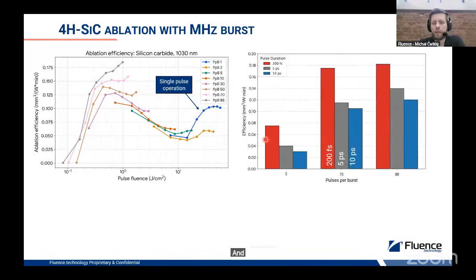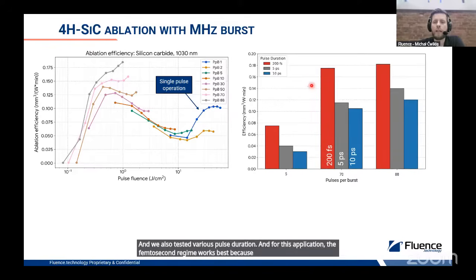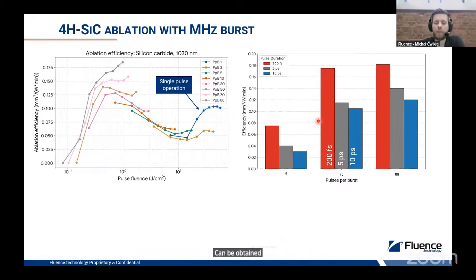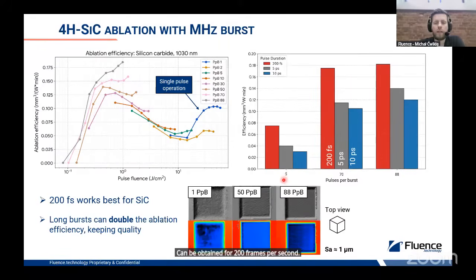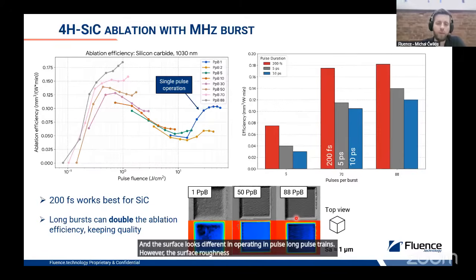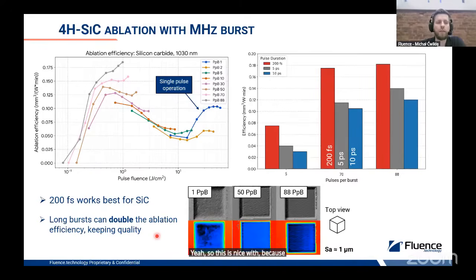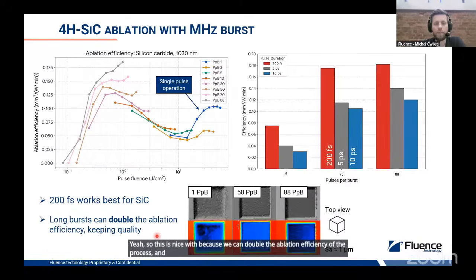And we also tested various pulse durations. For this application, the femtosecond regime works best, because maximum efficiency can be obtained at 200 femtoseconds. In this case, we also evaluated the surface quality, and the surface looks different when operating with long pulse trains. However, the surface roughness is still comparable to single pulse operation, which is approximately 1 micrometer Sa. So this is nice because we can double the ablation efficiency of the process and therefore the productivity.